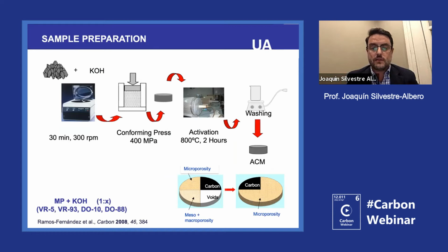And as we wanted to prepare narrow cavities, we decided to use KOH, because KOH is a very important chemical to develop carbon materials, as I say, with very narrow porosity. So we were mixing the petroleum pitch with the KOH in different ratios. We were working either with powder or with monoliths. And you can see here that one important point of the petroleum pitch is that you can make monoliths without binder. This is a system with what is called self-sintering ability. And at the end, we had, of course, an activation step at 800 Celsius, and finally the washing to remove the KOH.